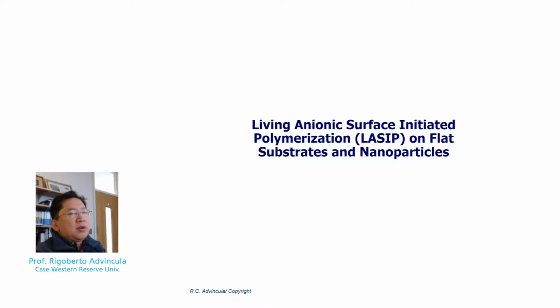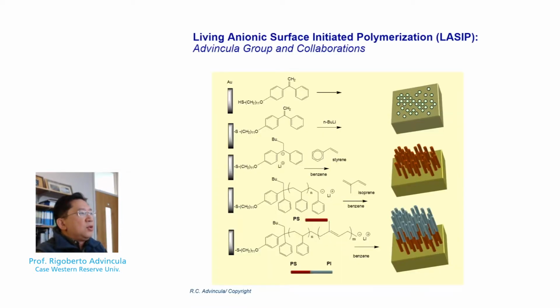So we were one of the first to pioneer what we call anionic polymerization on surfaces. We call this the LASIP technique. One technique that we used involved the tethering of diphenylethylene co-initiators, which were then activated by n-butyllithium. The anion generated allows us to, for example, polymerize styrene, or even form a block polymer brush with isoprene. Hence, a classical anionic polymerization, which is done in solution, we're able to do on surfaces. And in this case, a modified gold surface with a diphenylethylene co-initiator.